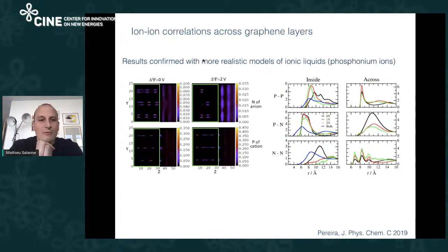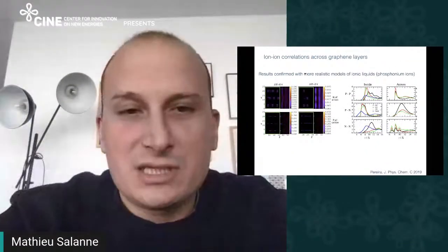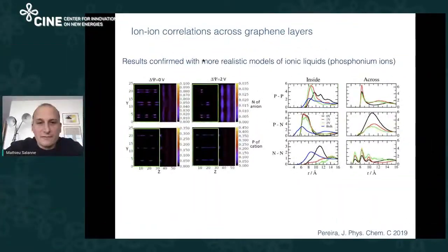And so we were able to interpret this result by saying that, in fact, you have your surface, you put an anion like this, and because of this, you will have a positive charge on the surface, and this will attract another anion. And so this is an interesting aspect of graphene. It's a kind of transparency of graphene that could be used in some device to increase the capacitance. But of course, you need a very high control of the porosity and of the structure of your material to really take full control of this result.